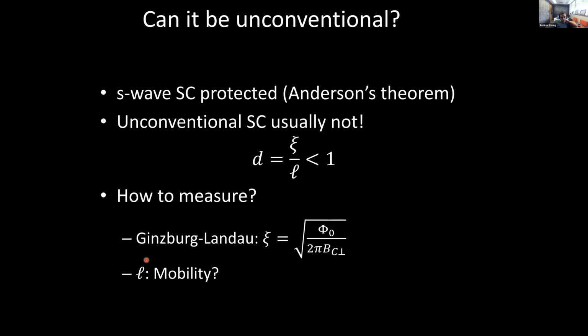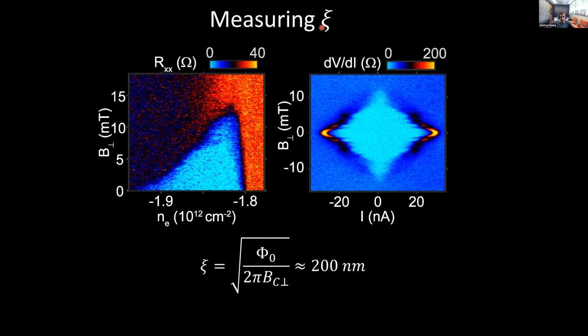And the mean free path you can measure basically from the mobility of the charge carriers. All right, so measuring xi is relatively straightforward. We simply apply an out-of-plane magnetic field, and we find that superconductivity dies at fields on the order of 10 millitesla. And so you can extract a coherence length of a couple hundred nanometers, which is just a number that we can keep in mind.